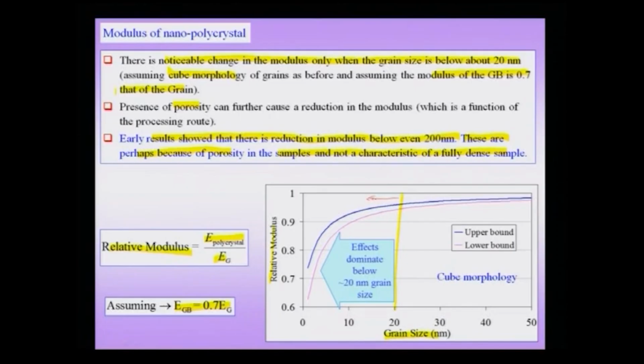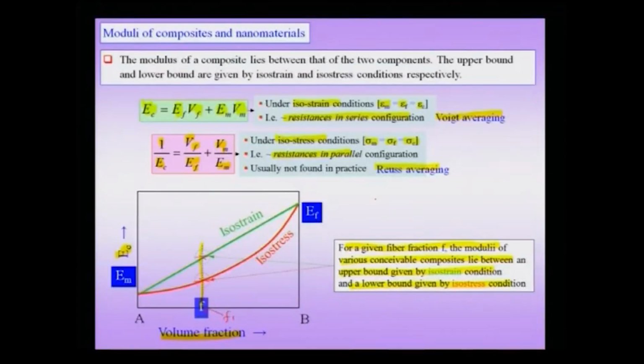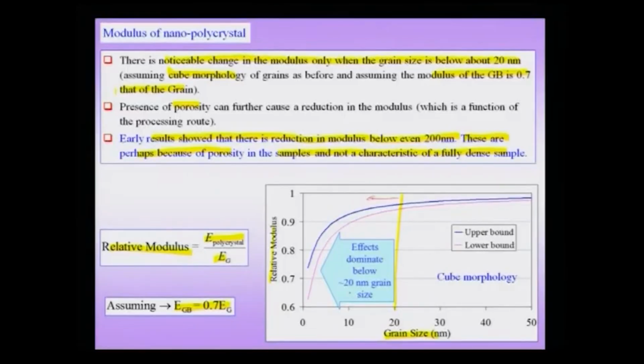Since I am assuming a composite, I obviously have to have an upper bound and lower bound as shown here, the upper bound corresponding to isostrain and the lower bound corresponding to isostress, and I see that for a 10 nanometer crystal, for instance, I can draw a dotted line like this. The lower bound is about 0.9 and the upper bound is about 0.92 or 0.93. Therefore, by using my understanding of composites, I can actually calculate the modulus of a polycrystalline material, and I see that the modulus of a polycrystalline material is lower by about 10% when you go down to small sizes, which is about 10 nanometers or below.